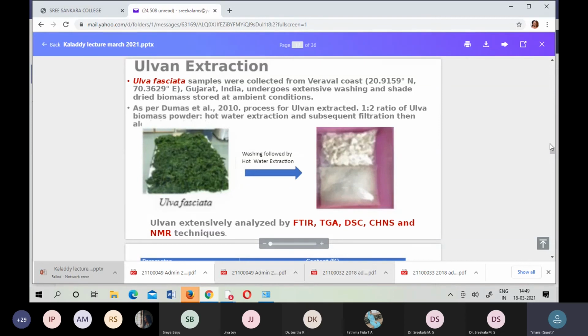So we end up getting a white or pale straw color material that is water soluble, coming from the same Ulva fasciata. It is not cellulose, but we are getting this, and we were able to make scaffold. We can even make some films.